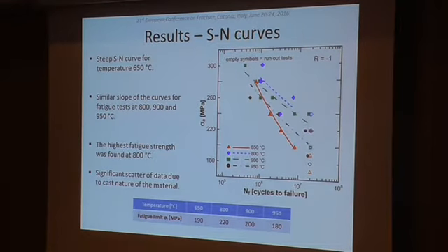Here are already some curves from our fatigue tests. You can see 4 curves representing each temperature, and from this diagram it's obvious that one curve, the curve representing tests at 650 centigrades, has a different slope than the other 3, and this is another evidence that in this material there is some change of damage mechanism, where at this temperature we observed the dominant stage 1 crack mode.